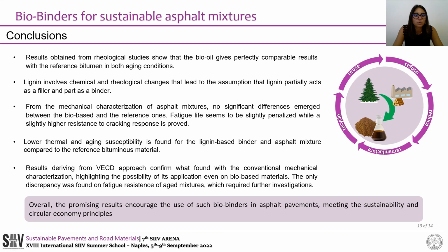Moreover, lower thermal and aging susceptibility is found for the lignin-based binder and asphalt mixture compared to the reference bituminous material. Results deriving from VECD approach confirm what found with the conventional mechanical characterization, highlighting the possibility of its application even on bio-based materials. The only discrepancy was found on fatigue resistance of aged mixtures, which required further investigations. Overall, the promising results encourage the use of such biobinders in asphalt pavements, meeting the sustainability and circular economy principles.